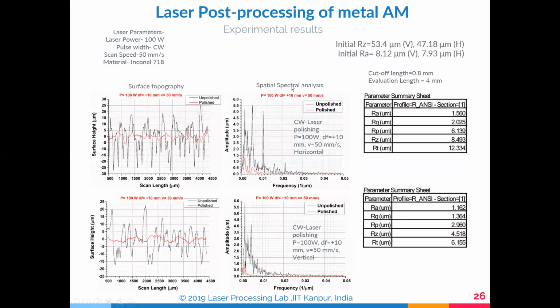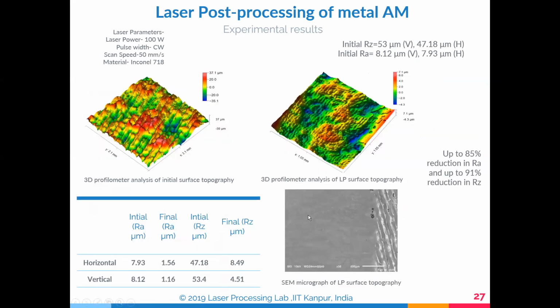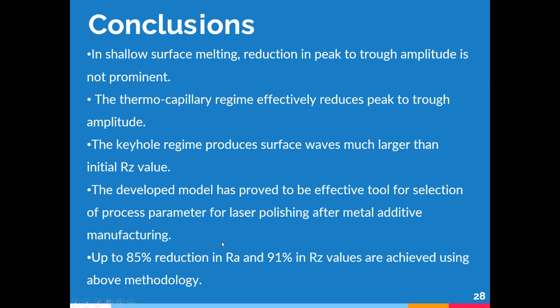So for the surface topology, the spatial surface topology, we got the results. So these are some of the experiments which were conducted, and this is what it is. Initial roughness was 7.8; horizontal and vertical, we were able to get 1.5 and 1.6, and Rz values were there.